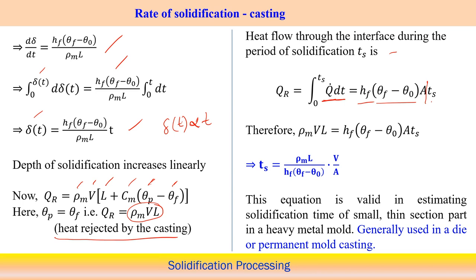Now, this is Q R calculated one way: the total heat release during the solidification period through the interface. The other way is the total amount of heat rejected by the cast volume, which we have also calculated. If we make this energy balance, both are the same, and here we get T s equal to rho m L over h f (theta f minus theta 0), into V by A.